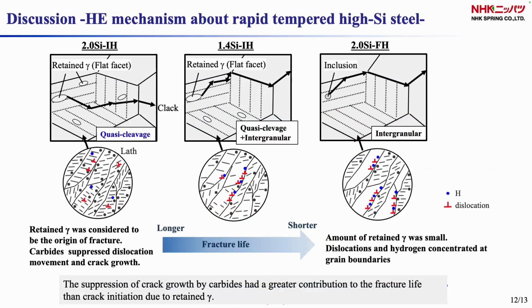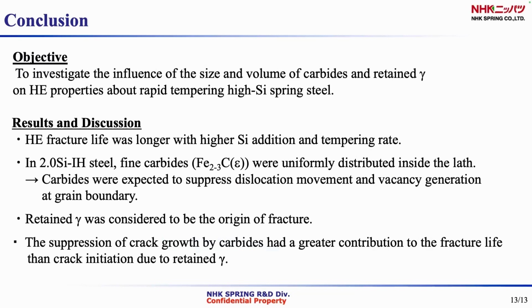Finally, we summarize the hydrogen embrittlement mechanism of the high silicon steels. 2.0Si-IH steel, which has the longest fracture life, contains much retained austenite. Retained austenite was considered to be the origin of fracture. On the other hand, many carbides within the grains suppress dislocation movement and crack growth. In contrast, the other two steels have less retained austenite, but dislocations and hydrogen are transported and concentrated at the grain boundaries. In this study, the suppression of crack growth by carbides had a greater contribution to the fracture life than crack initiation due to retained austenite. This is the conclusion, and thank you for your attention.